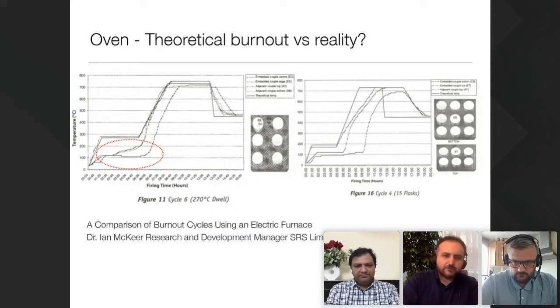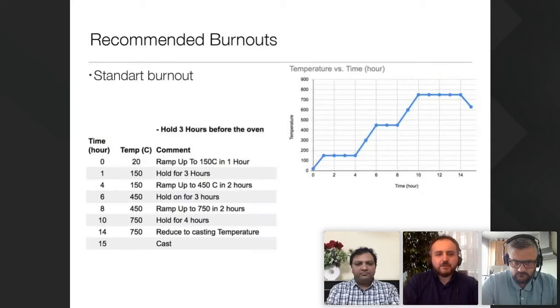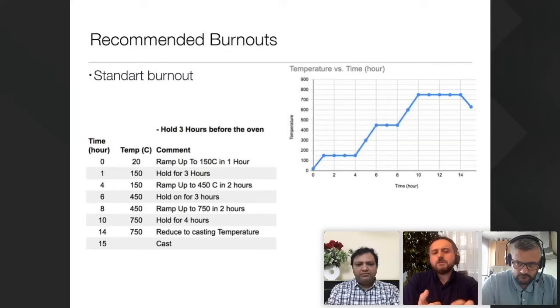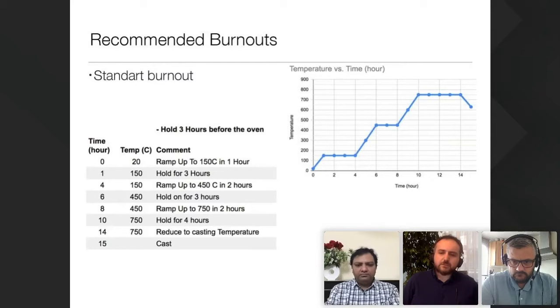So this is just a note about what is really happening versus what you think is happening. So here I put a recommended burnout, but please take all those burnouts according to your investment powder. The first thing I always say, at least with our resin, because we know it's very easy to cast, is first follow properly the whole steps of the investment manufacturer's recommendation. Check the mixing time, the temperature, the burnout that the manufacturer of the investment provides. This gives you a reference, a benchmark, so if you want to try different burnouts, you know what happens compared to what the manufacturer is telling you. Trust me, if you follow what the manufacturer says and you have proper investment, 90 to 99% of the time you will have very good casting, at least with our resin.